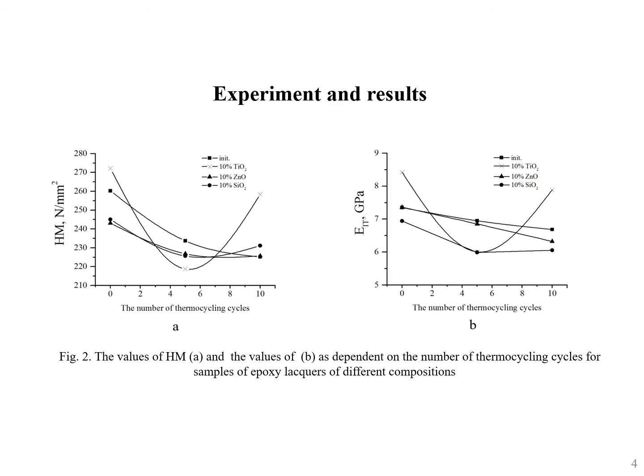Titanium dioxide has been found to increase Martens hardness by 5% as compared to that of the unmodified lacquer. In turn, the introduction of zinc oxide and silicon dioxide reduces hardness by 4% and 5.5% respectively. The value of modulus for the coating modified with titanium dioxide increases by 15% as compared to the pure epoxy lacquer, to become 8.4 gigapascal.